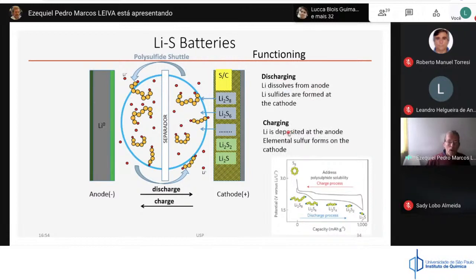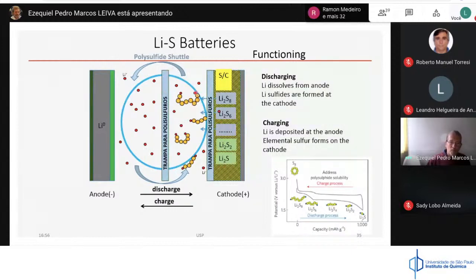Now, how can this problem be solved? For the problem of the polysulfide shuttle, one approach is to put a separator here, something that separates the cathode from the anode and tries to prevent the migration of polysulfides. Another approach, instead of putting the separator, is to put some material here which is able to retain polysulfides. This makes a trap for polysulfide. You can put a trap here, or you can put a trap here. The difference is that in case you put something here, the material you're putting here may also have a catalytic effect. That is something which is also considered by DFT calculations now.